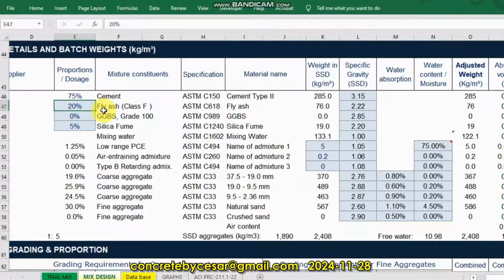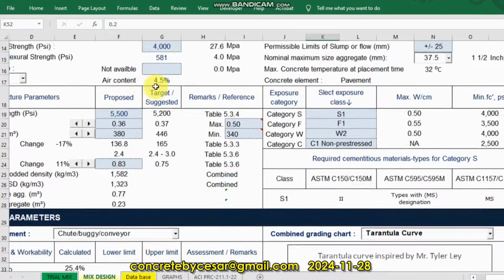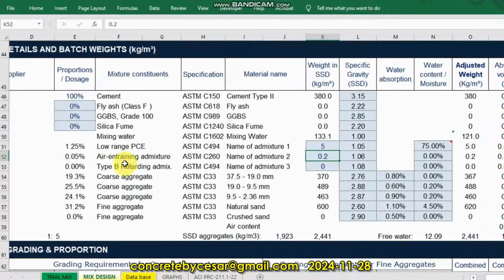So in case you are required, then you can use this portion to supply the percentage of your cementitious materials. For the admixture, for this example, in my experience, I have used low range PCE, or in between low range and mid range PCE. So I estimated to use like 5 kg per cubic meter. I need also air entraining admixture, 0.2 kg. Since we have here 4.5% air content, to achieve that you need air entraining admixture. It could be more, maybe 0.3, 0.4, depending on the trial mix result.